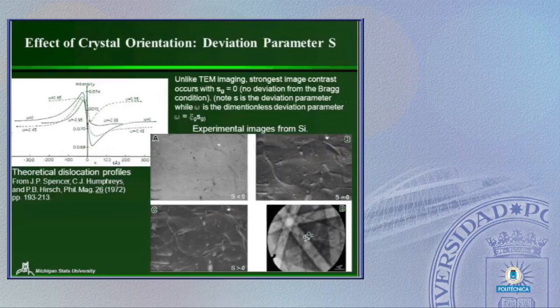And this shows, again, a number of theoretical profiles. And again, this was all thought about really 40 years ago by Hirsch's group. And they sort of gave it up because they didn't really have good microscopes for doing it. And so you can see that if our dimensionless deviation parameter is equal to 0, this shows the maximum peak-to-peak contrast associated with this. And so what I've shown here now are some experimental images that we've done.